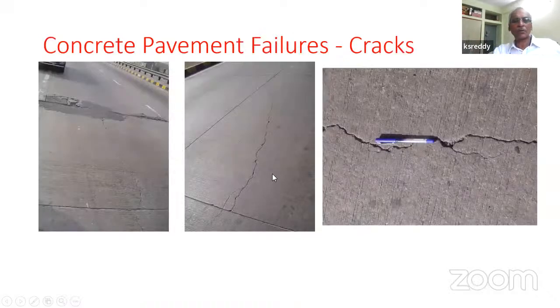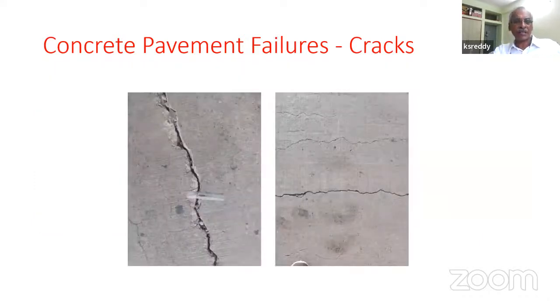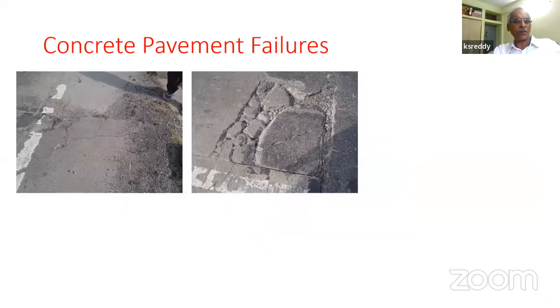These are typical problems that we have with concrete pavements, various kinds of cracks, narrow cracks, large cracks, and depending on the position, corner cracks, mid-slab cracks, and so on, full length cracks, full depth cracks, wide cracks, and so on. You can see these are cracks where there is faulting also there. Both slabs are at different elevation. So there are various types of cracks that form because of various reasons. And once you have cracks, you have other disintegration of the slab that is occurring near the corners and mostly near the joint locations. And at edges of cracks, you have the slab disintegration happen.